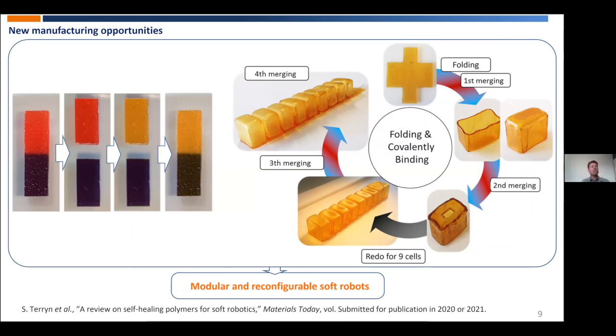So you can actually cut parts at the interface, then swap one of the materials and put it back together, apply heat and cool down, and then it will be bound again. So I think these new materials open a lot of possibilities for modular and reconfigurable soft robots in the future. And we showed also that we can do a transformation from 2D structures to 3D structures.